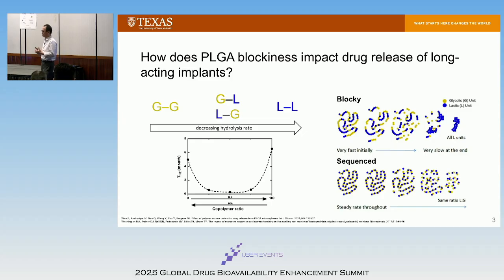When you make PLGAs, you start with glycolide and lactide. But glycolide is very reactive. There's a reactivity ratio, so it goes from GG first, then lactide inserts in. That's how PLGA is made. It's not by a condensation reaction. It's a ring opening polymerization process.